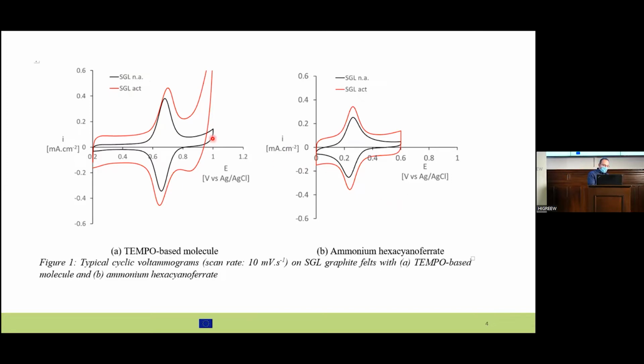What you can see here is a difference between activated and non-activated, but it is essentially what we call the capacitive current. And regarding the activity, we have oxidation and reduction peaks. When we look at this cyclic voltammogram, we don't see much difference. This could be good news. It means that any material provided by a commercial provider will be very good for this reaction.